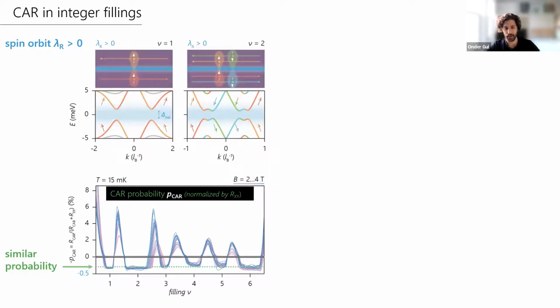Our calculations show that the pairing mechanism, so this is also an interesting point, the pairing mechanism for even and odd fillings are the same, considering an ideal interface. This is because edge modes pair with their own counter-propagating partner. So the edge mode of filling factor 1 pairs with the edge mode of filling factor 1, and the next higher edge mode of filling factor 2 pairs with, again, the filling factor 2, and basically the pairing is always a spin polarized channel. But this is considering an ideal interface.